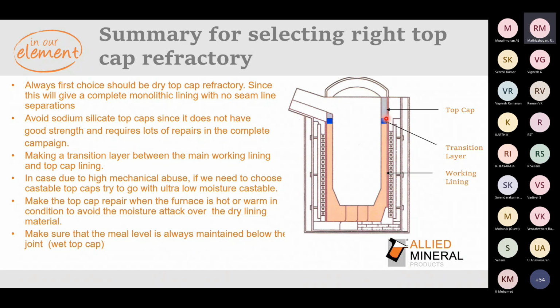In case you have high mechanical abuse, we can go with ultra low moisture castables as a top cap material. But do this castable lining when the furnace is in warm condition, so the moisture is not absorbed by the dry ramming material at the bottom. Also, whenever you use a top cap material other than dry top cap material, make sure the metal level is always on the main working lining and does not come to the level of the top cap materials.